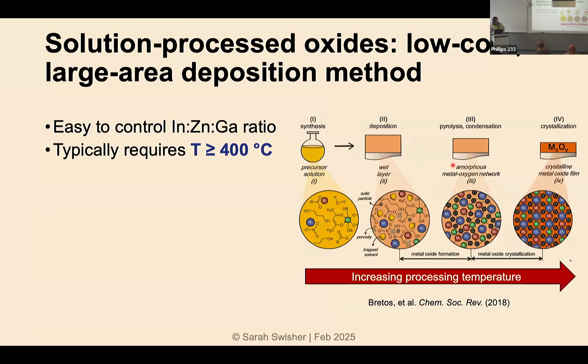Now, some people, if you tell them that you're working on solution processing, they say, oh, that's cute, and printing, isn't that fun? But actually, solution processed oxides are really fantastic, even if you don't care about printing or additive manufacturing at all. We spin coat these materials. It is as simple as mixing an indium salt, like indium nitrate, with zinc nitrate into a solvent. Those salts dissolve, and you can spin coat a layer and then heat it up to 500, 600 degrees, something like that, and get a very nice semiconductor film. So we're actually exploring this to see how these films compare to something like the ALD oxides that a lot of people have been exploring. So the problem with these is that this salt gel method does require about 400 degrees or higher to convert those indium and zinc salts into the metal oxide form that you want.